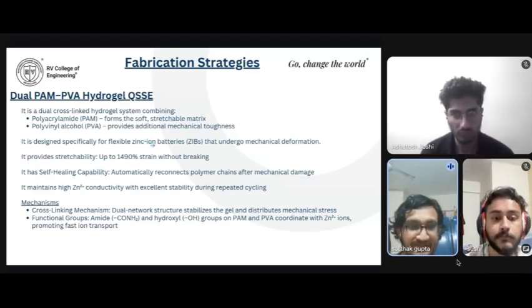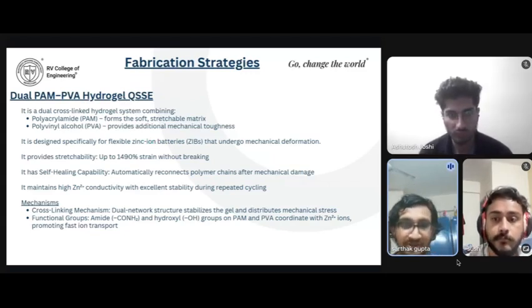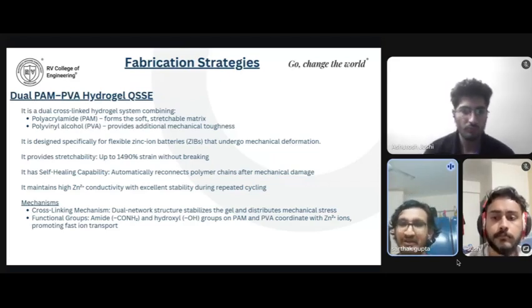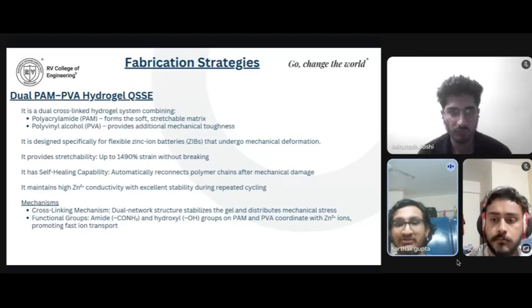As I mentioned, the mechanism is cross-linking: a dual network structure which stabilizes the gel and distributes mechanical stress. Functional groups, such as amide CONH2 and hydroxyl OH groups on PAM and PVA, coordinate with Zn2+ ions, promoting fast ion transport.